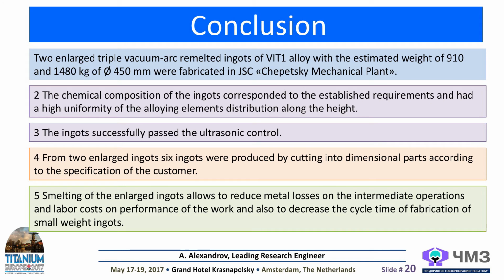So, the conclusion of this work. We made two enlarged triple vacuum arc melted ingots of weight 910 kilograms and 1480 kilograms. The composition of the alloy has 7 alloying elements. The chemical composition of the ingots corresponded to the established requirements and had a high uniformity.